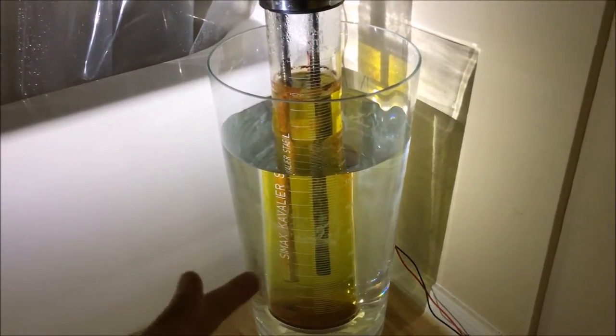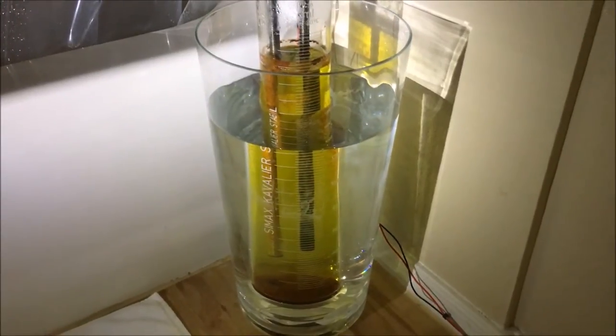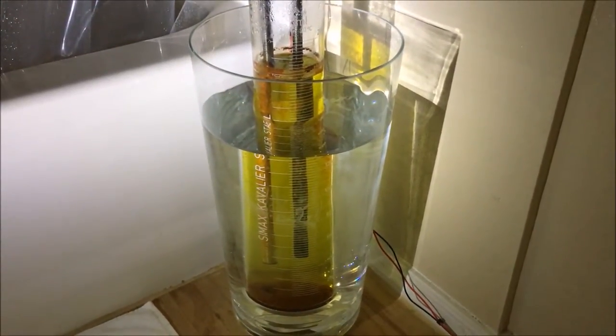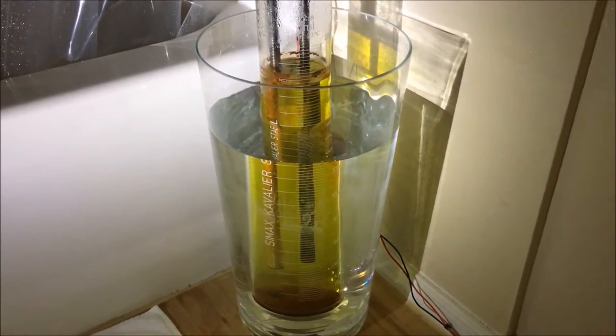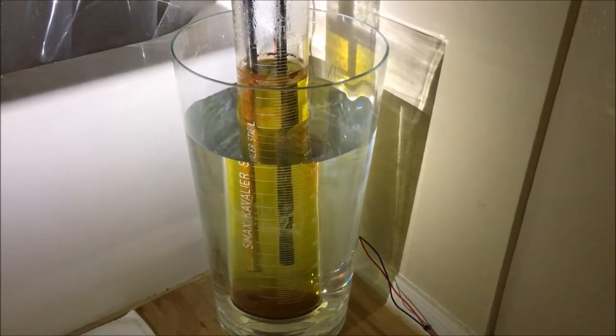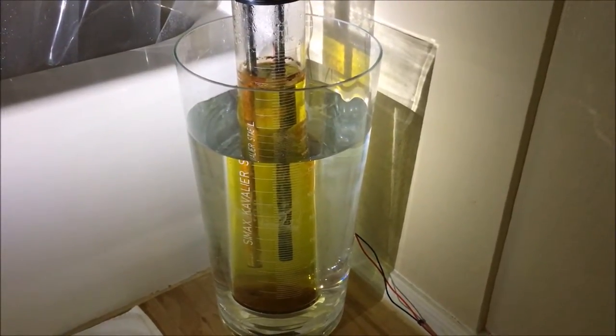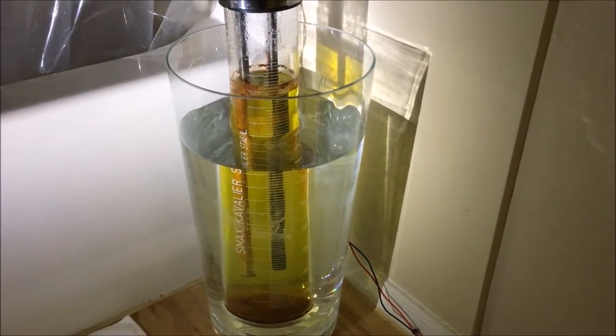What that means is since the electric potential of a hydrogen oxygen cell is approximately 1.23 volts, really you should only be a few tenths of a volt over that in terms of the power supplied to it. Now I supplied this system with 12 volts because I needed to get the current quite high in order to produce the amount of gas I wanted to.